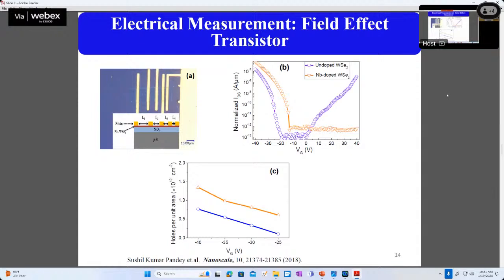So from ambipolar FET to p-channel FET, we are able to make it by niobium doping. Similarly, there is a way to calculate the carrier density, and that is done here also. We found that if the gate voltage increases on the negative side, the holes per unit area increase, especially because the electric field is more at the gate. This material is very thin, so you will get higher hole density in the layer.